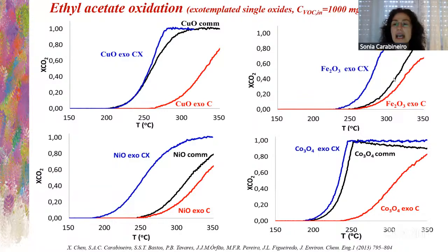So we have here the commercial samples. They are in black. So copper oxide, iron oxide, cobalt oxide, and nickel oxide, the commercial samples. And then we have the exotemplated samples with activated carbon. They are worse, as we saw, because of the ashes.